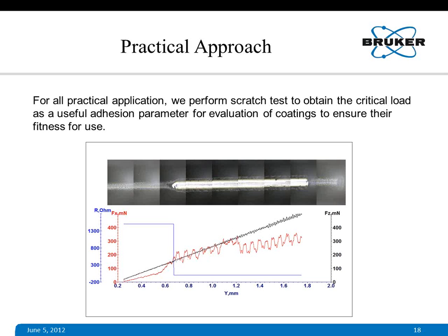So this is a practical approach where we find the normal force, or critical normal load, where the coating fails. And this particular parameter can be used as a comparative parameter for comparison of several coatings. If it is pretty high, it implies that the coating is good, the scratch adhesion of this coating is good. If it is low, it means scratch adhesion is low.